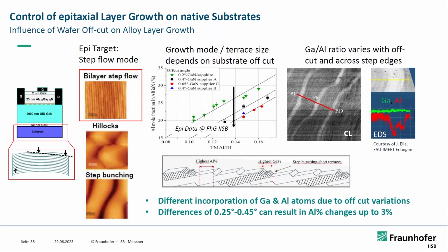So we really have to carefully control the growth mode in epitaxy. And this variation of off-cut really is making a big issue. So here you see this bilayer step flow, which is an AFM picture. This is what you want really, and this is what you have.